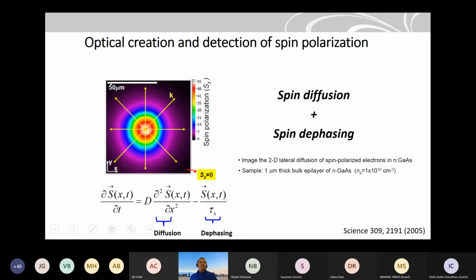So here the scale bar is 50 micrometer. It's a gallium arsenide semiconductor. It's a bulk material. So they shine this polarized light and you create spin polarization. The maximum spin polarization is, let's say, 55% here in the middle of the sample. And as you see from the color code here, the spin polarization goes to 0 with distance. Okay, so what can be happening here?